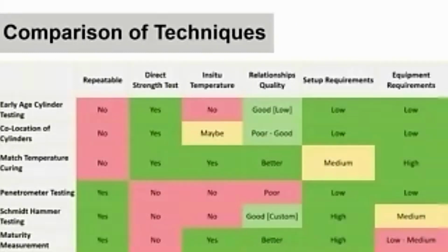So coming back to our techniques, again, the direct measurements of the normal early age cylinder test where we cure them at lab conditions and break them early, the co-location of cylinders in the curing environment, or the creation of a specialized curing environment that matches the temperature on site, have the advantage of we're still doing our compressive strength test. Match temperature curing also has the advantage of catching in situ temperature, and the co-location techniques certainly endeavor to do so as well. The advantage of catching in situ temperature is if it's hotter on site, strength gain will occur more quickly. So by using an early age strength technique that captures in situ temperature, we can actually attempt to better model strength on site with either our early age breaks or using a correlated relationship.